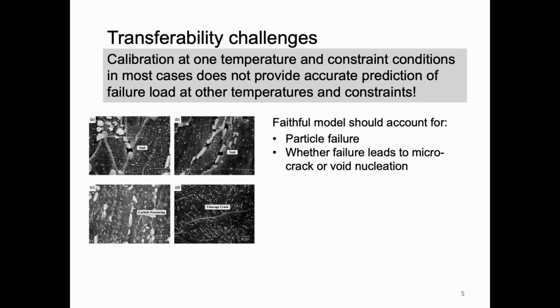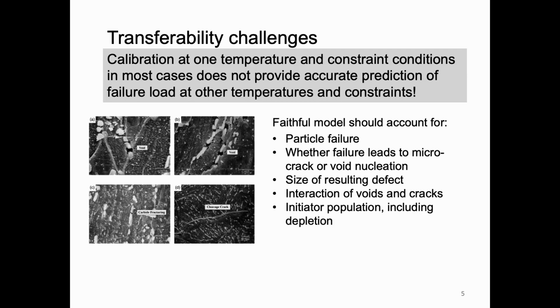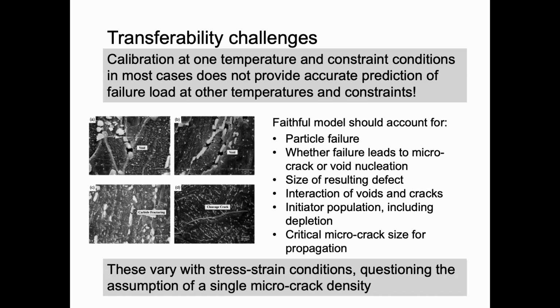This is particularly relevant to the ductile to brittle transition regime. It should be able to say what is the size of the defect out of this particle failure. It should be able to account for interaction of voids and cracks. It should be able also to account for the population of initiators, which is a measurable property by metallography, including the fact that there may be a depletion of these particles with the load. And it should be able to say what is the critical microcrack size for propagation.